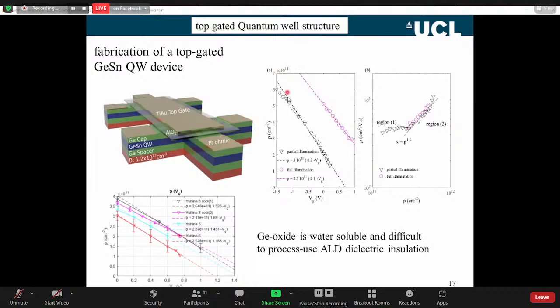This is at lower temperatures. You can see the hole density as a function of gate voltage again. We can either go into enhancement mode, so we can apply a negative gate voltage, and push up to something like 6 times 10 to the 11. The ungated devices have about 4 times 10 to the 11 carriers. These devices, we can push them up to about 6 times 10 to the 11. Very clearly metallic. In the depleted region, they go very, very insulating.